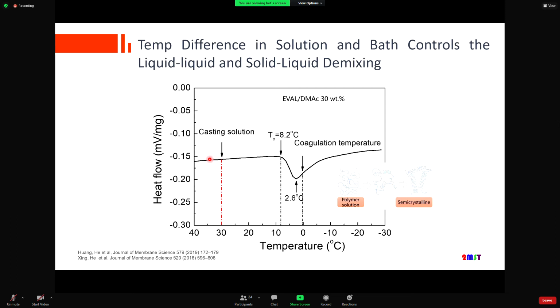Different from the PEK system, we developed another methodology to analyze how to control the membrane morphology. We use the temperature difference between the polymer solution and the coagulation bath to control liquid-liquid demixing and solid-liquid demixing. Solid-liquid demixing is because of the crystallization of the EVAL polymer. We took the polymer solution and decreased its temperature. You will see here at about 8 degrees Celsius, there is a peak. This is because of the crystallization of the EVAL polymer, and there we release some heat. We call this transition temperature the crystallization temperature of the polymer solution.